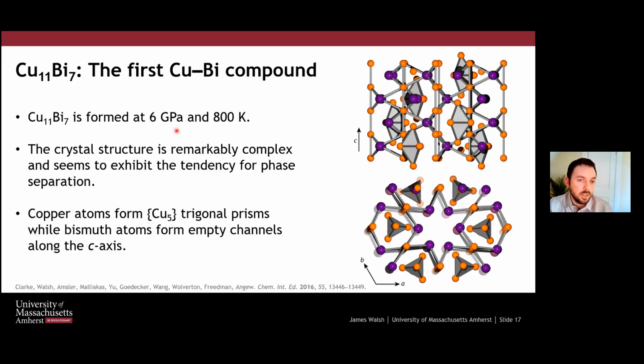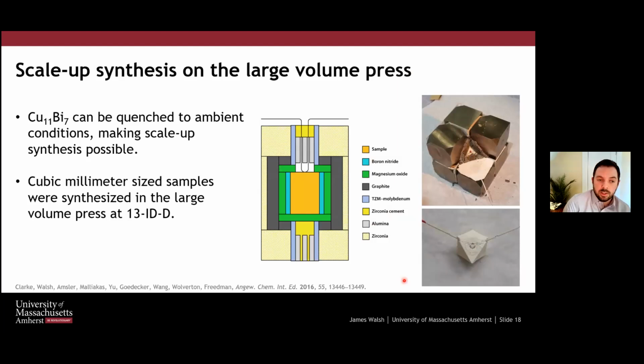So this was at 6 GPa and heating to 800 Kelvin. The nice thing about having a relatively low pressure, so with the iron bismuth, we had to go to 30 GPa, and this copper bismuth, we only needed to go to 6 GPa. And so what that allows us to do is to use large volume press methods. And so in the large volume press, it's larger in scale, so it's not a handheld device anymore. It can take up, you know, half a room. But the benefit is that we can have a much larger amount of sample. So we can get to cubic millimeter scale samples in the large volume press.